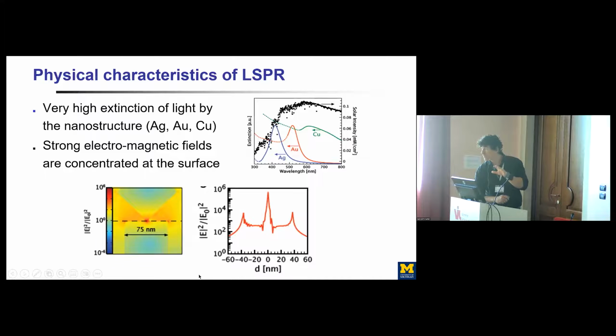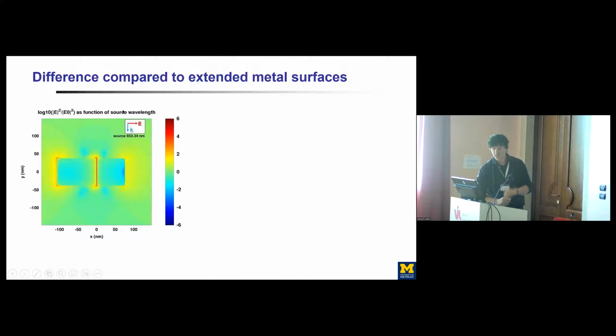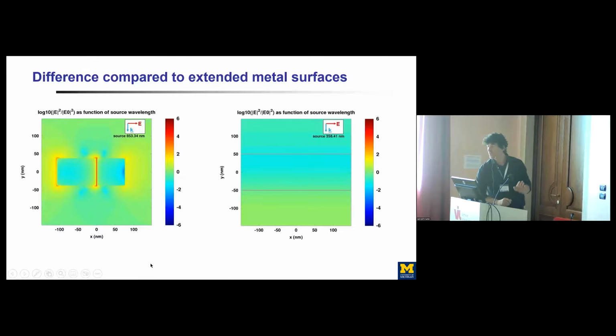So for all intents and purposes, you are localizing the energy of the light that's hitting this dimer of silver nanoparticles at the surface of the nanoparticles, and particularly between these nanoparticles. You see that these enhancements in field intensity are anywhere between 10 to the 3, 10 to the 4, all the way to 10 to the 6 compared to the incoming energy of photons that are hitting this system of two nanoparticles. So this situation is actually fundamentally different from an extended silver system.